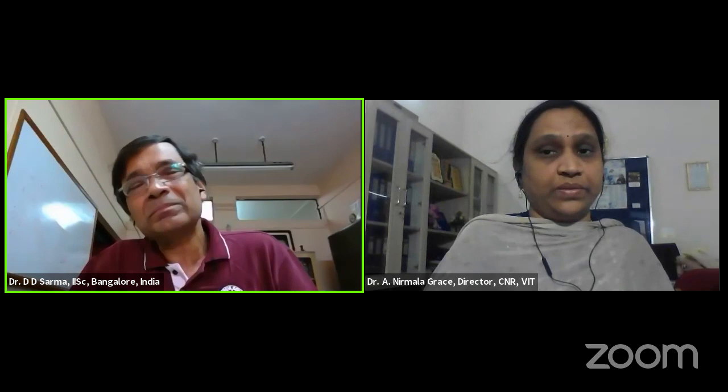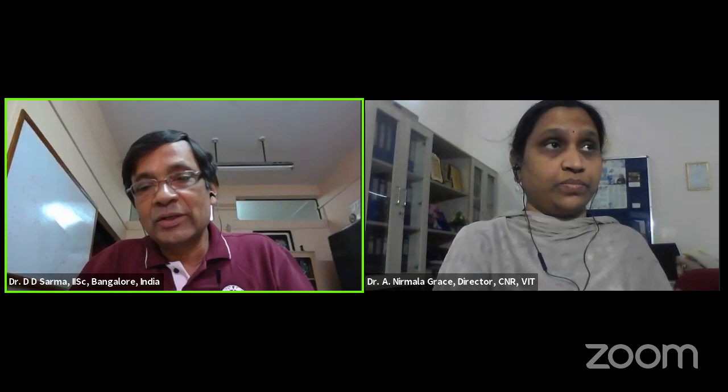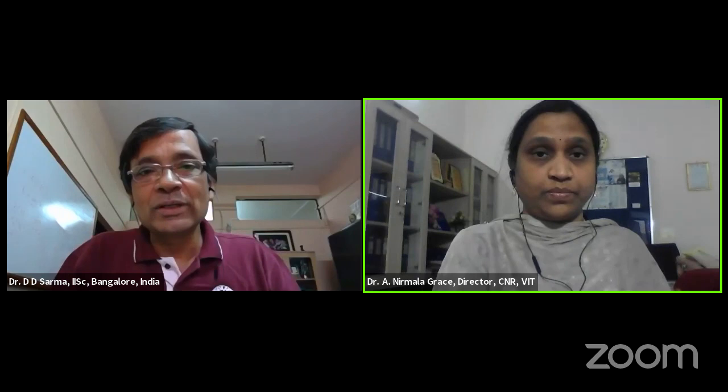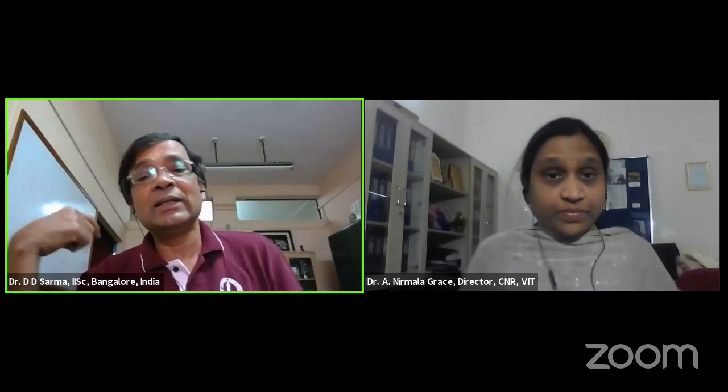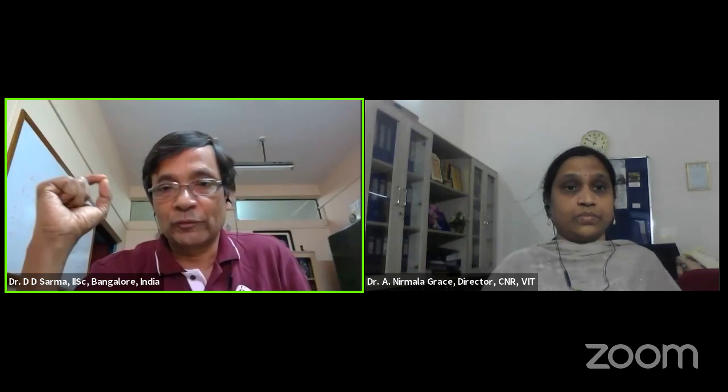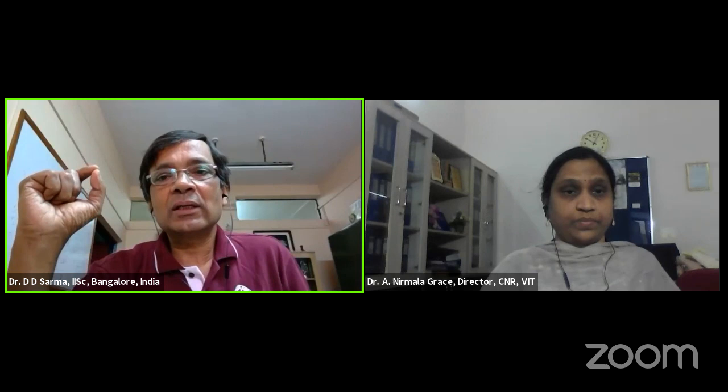You have to understand what XAFS does and what it doesn't, what it is good for and what it is not good for. It is not good for determining the bond distances with great accuracy. I may offend some XAFS practitioners, but I also use XAFS extensively. It's difficult to pin down bond distance differences finer than 0.05 angstrom, particularly in a mixed state, which means that the subtle dimerization, et cetera, will be very difficult to see in XAFS. So it'll depend on a lot of data massaging trying to get answers out.